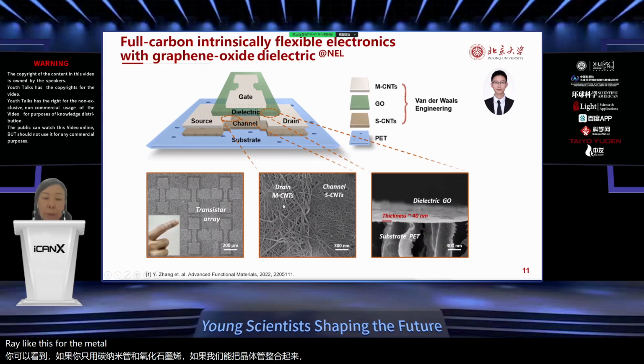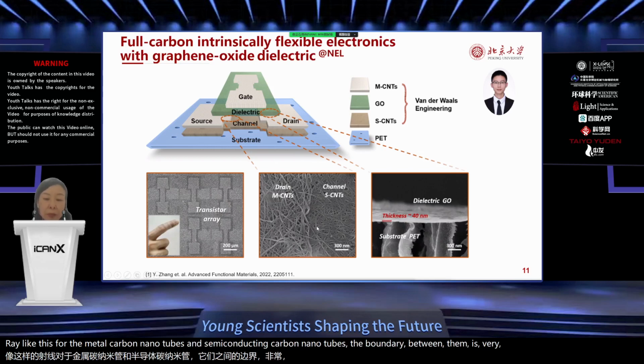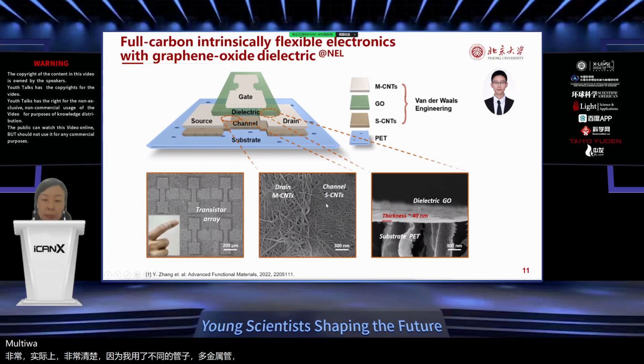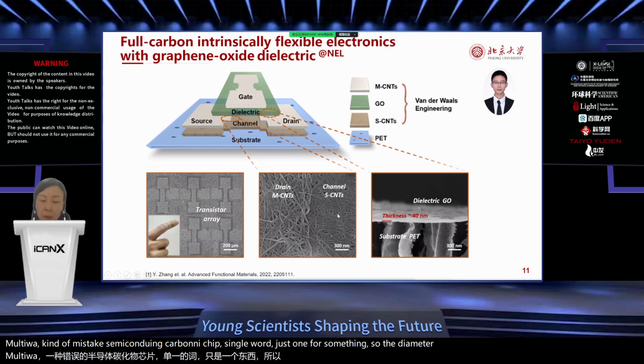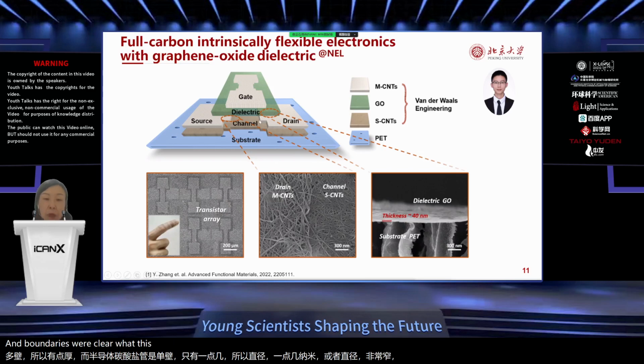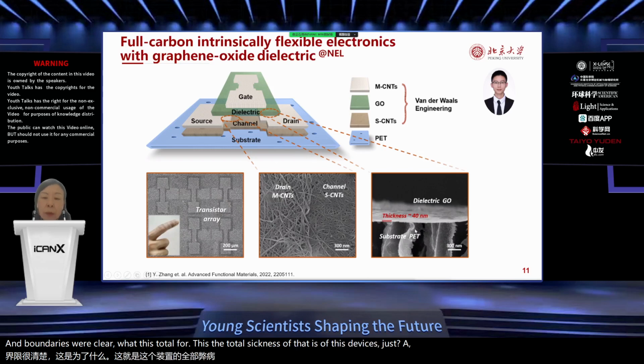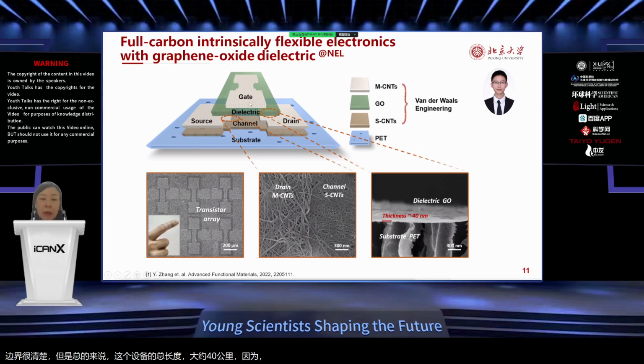For the metallic carbon nanotubes and the semiconducting carbon nanotubes, the boundary between them is very clear because they are using different tubes, and the metallic tubes are kind of multi-wall, so they are kind of thick, and the semiconducting carbon nanotubes are single wall, with a diameter of just 1 point something nanometers, so the diameter is very narrow, and the boundary is very clear. The total thickness of this device is just around 40 nanometers, because every layer is kind of a network or kind of a particle film, so it's very thin.